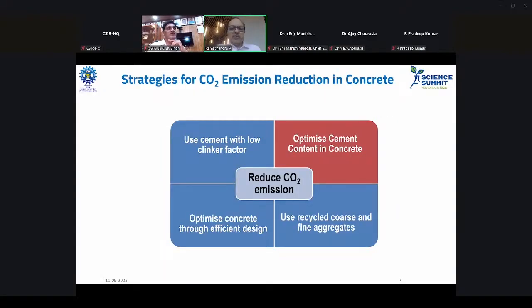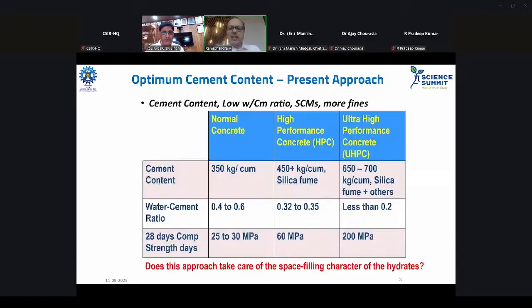The second, just before going to the second one, I would like to mention that the Bureau of Indian Standards has brought out low clinker cements. One is the composite cement with 45% clinker, and the other is LC3, limestone calcined clay cement, with 50% clinker. Therefore, to that extent, clinker reduction happens through these newer varieties of cements. Now, going to the second possibility, optimizing cement content in concrete.